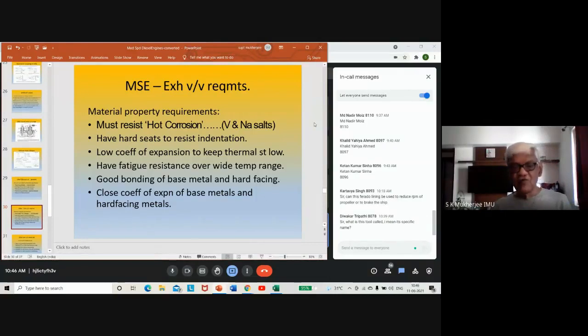So that seawater, when it is evaporated, the water goes away, but the sodium salts, that is sodium chloride, magnesium chloride, calcium sulfate, all are there. Sodium chloride is the largest constituent. So this sodium from there reacts with the vanadium during combustion to form sodium vanadates. And these are very, very corrosive and they cause corrosion to the extent that you saw just now. And that type of corrosion is called hot corrosion. Cold corrosion is corrosion with sulfur. When sulfur forms sulfur dioxide during combustion and it combines with the moisture to form sulfuric and sulfurous acid, and then you have corrosion of the components, that is called cold corrosion.